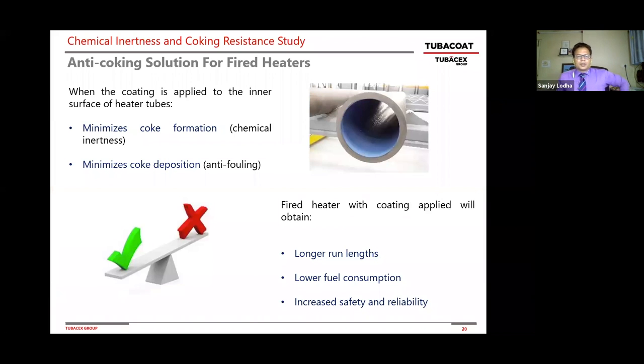So the coated tubes have two things that work very well for the heater tubes. One is these coatings are chemically inert, so they minimize the coke forming reaction. Second part is, once you form the coke, does it stay in the coker furnace tubes or does it move further to the coker drums? It has this anti-fouling, very smooth, anti-fouling surface that allows minimum coke deposition. And because of these two properties, you get significantly longer run length between the spallings or coking.